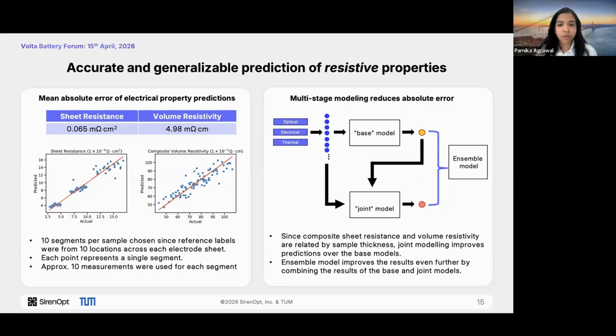What we employed here was a multi-stage modeling approach. The original modeling approach I talked about a few slides ago was to use our physics-based features to calibrate a base model and connect that with the final properties. What we can also do here is leverage physics-based relationships. We know that sheet resistance is related to composite volume resistivity by thickness. Instead of explicitly calculating that by assuming a thickness value, we created a joint model which has not only the physics-based features as inputs, but also the output of the other model as an input. When we use the joint model, we see that the predictions improve.